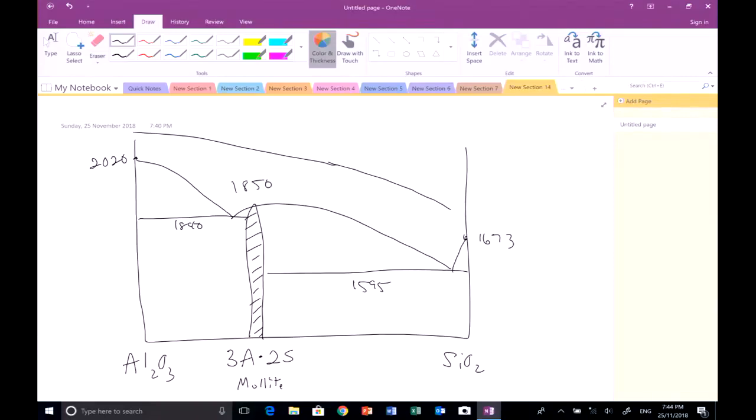I did the government house a number of years ago, but I did this other one just recently. And the reason why that mullite was there was because I've got a book that talks about early brick making in New South Wales, and the author says that most of those bricks were fired at 900 degrees for 3 to 4 days. And typically you need 1,000 degrees to make mullite form.